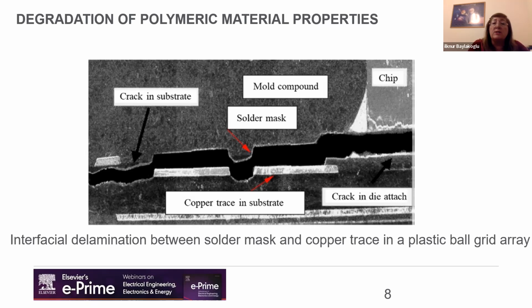During this moisture absorption of these plastic materials, they can cause some popcorning mechanisms during the reflow process. Because of this high temperature, the absorbed moisture vaporizes and expands with a high stress, and it can cause cracking of the material.